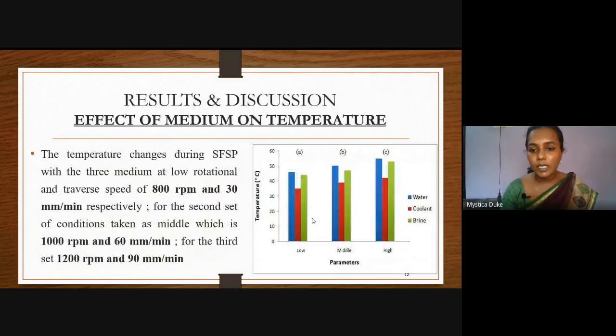So here you can see that the blue is the water. You can see water provides maximum temperature change in all the combinations. Temperature change is nothing but the change between the initial and the final temperature. So water provides maximum temperature change. This is because water possesses high specific heat capacity, so it can take away a large amount of heat for a large amount of time. This is why we found that water could provide maximum temperature change.